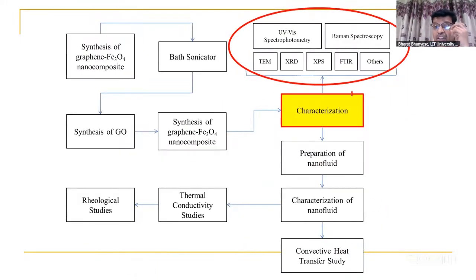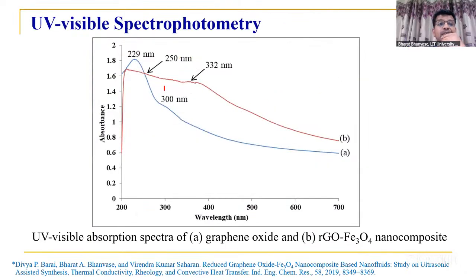Here for characterization, this is UV-visible. The blue line shows graphene oxide, having characteristic peaks at 229 and 300, which confirms the formation of graphene oxide. Another one is RGO Fe3O4 nanocomposite, with peaks at 332 and 250, which confirms the conversion of graphene oxide into reduced graphene oxide and loading of Fe3O4 nanoparticles on it.